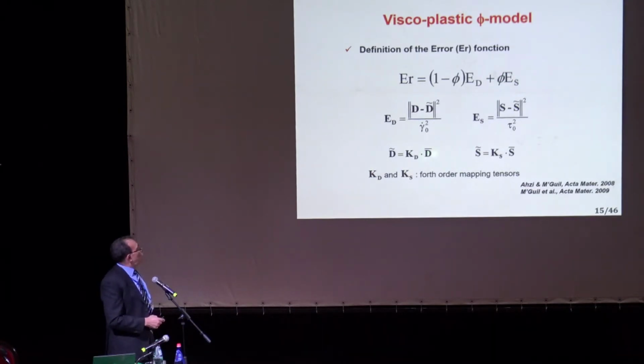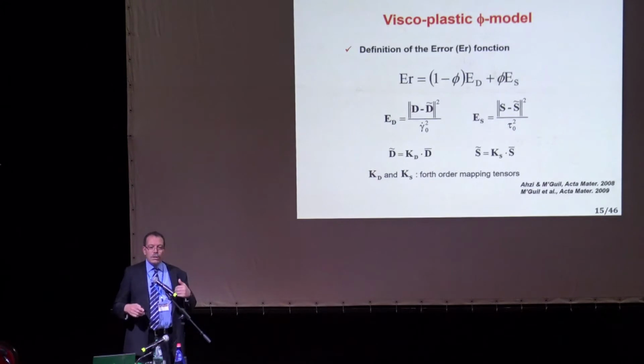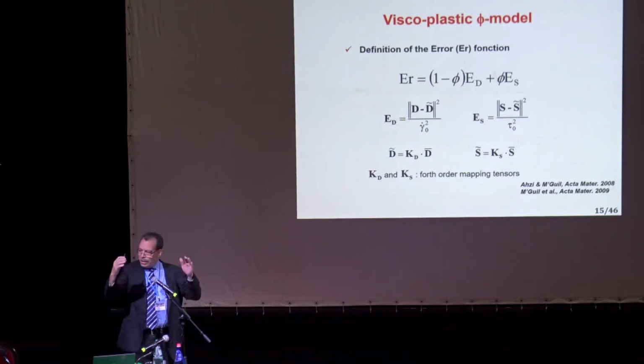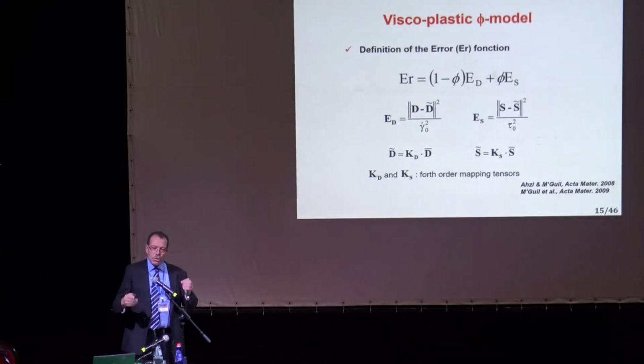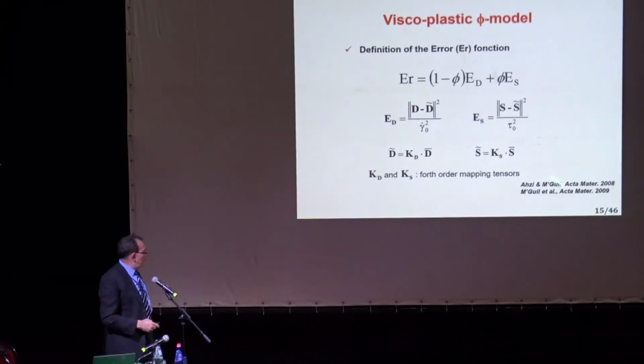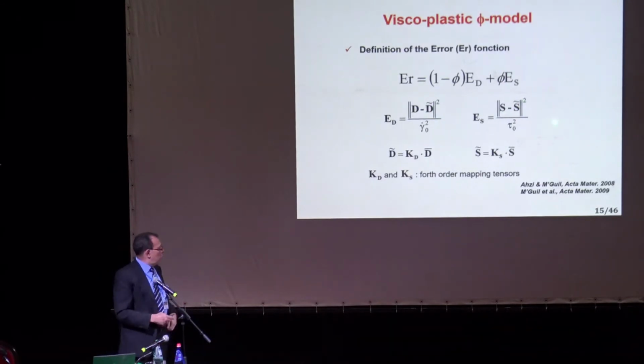Okay? So we minimized, by the way, I used this d tilde and s tilde, in fact, as what you naively get if you average your local fields. When I say naively, you may not get the macroscopic stress or macroscopic strain. So we have to go through a normalization procedure in order to make sure that your average conditions are met. And they are related to the macros. These are macroscopic quantities by these tensors that we will evaluate later on. Okay, but anyway, we could put D bar and S bar. We just want to make sure that at the end we have the global conditions met as well.